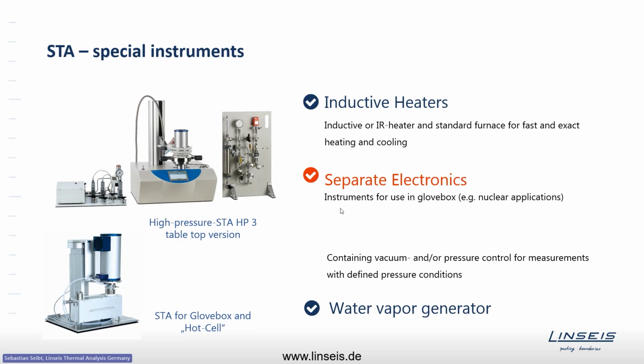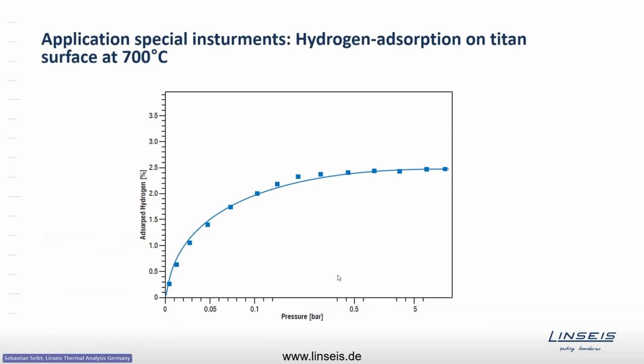And also for this special configuration, I have some slides here, and this shows you multiple curves in one diagram. This is the hydrogen absorption on the titanium surface. So at 700 centigrade, hydrogen was applied on a titanium sample at different pressure levels, starting at a low pressure. At a very low pressure, hydrogen was added, and once the signal was stabilized, the mass change was recorded. Then the pressure was increased a little bit.